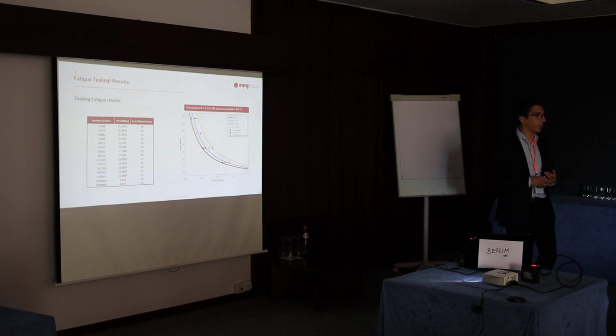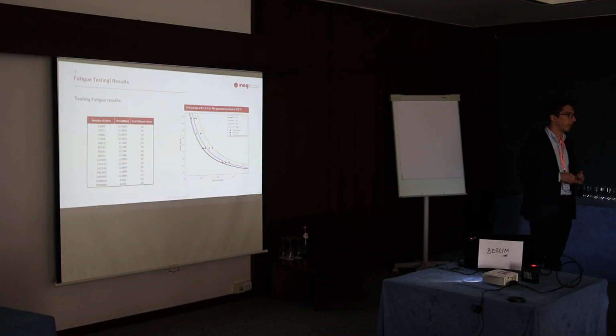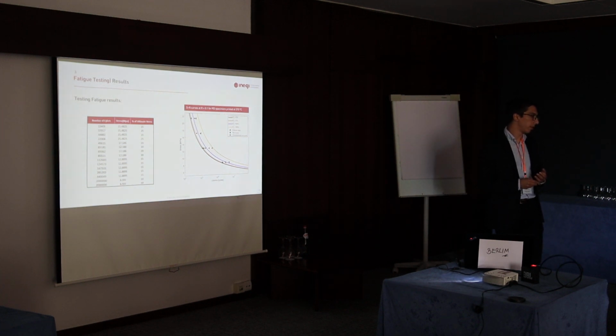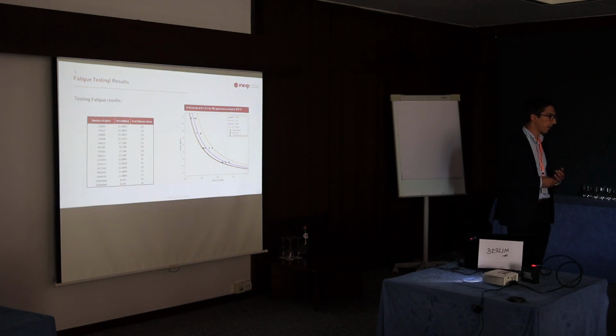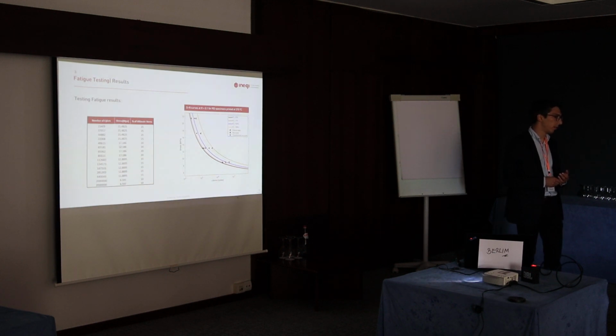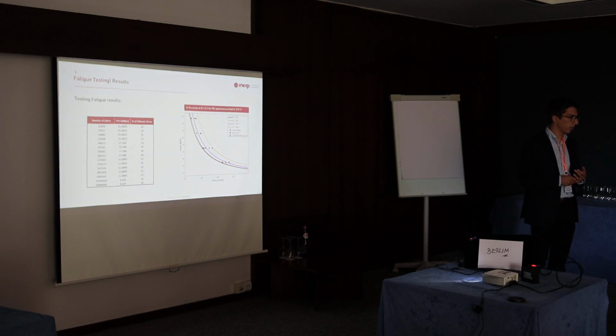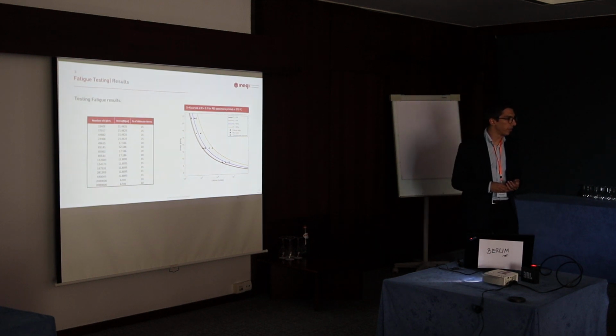The only thing I did, considering the frequency problem in fatigue, is monitor the temperature during the testing, using a thermographic camera to make sure that I have no variation in temperature, so I would have no thermal effects affecting the fatigue life of my specimen. With regards to temperature, first of all, you're only looking at the surface temperature, not the internal, right? So you don't know how much internal heating is going on. Okay. But it's not just the temperature. The strain rate has a very significant effect on fatigue of thermoplastics. Okay, I will make sure to consider that in the future. Thank you.